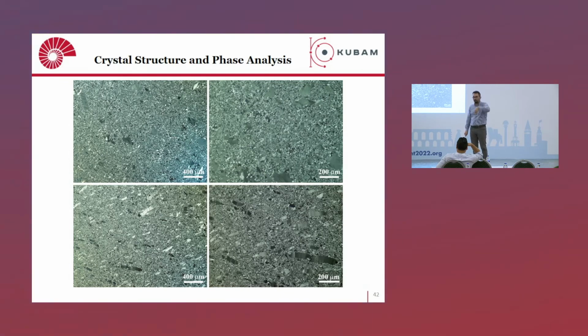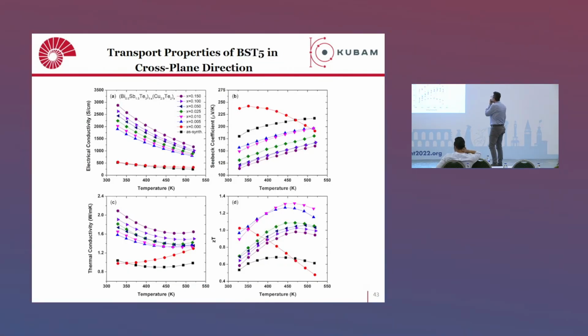This is perpendicular to the SPS direction. This is also nice because it can improve the electronic transport through the in-plane direction. So here are the transport characteristics. You can see that this is the undoped material, with low electrical conductivity. If you dope it with copper telluride, you can really tune it with the copper telluride amount, and the electronic conductivity goes up all the way.